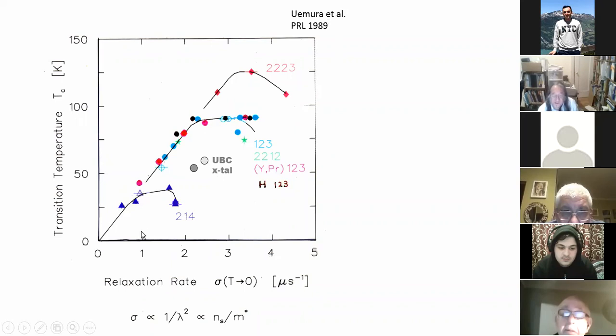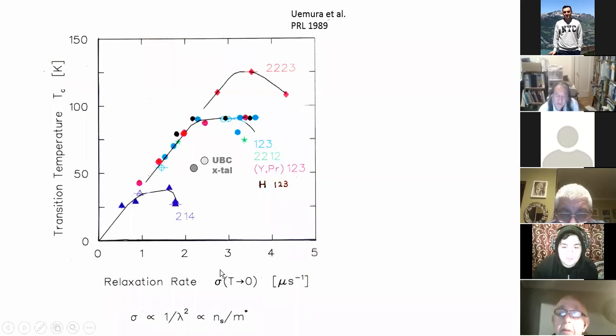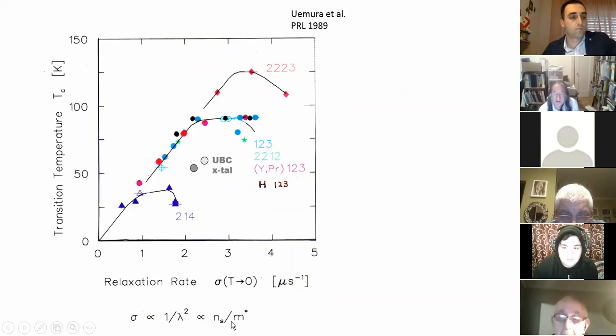And in the high TC cuprate systems, it is known that initially you dope superconductors with charges, essentially superconducting charges, and the TC increases and then shows some saturation and then decreases. But this initial increase area is called the underdoped region. And this data is showing that TC of this high TC cuprate superconductor, at least in this initial increase region with the doping, is related with a nearly linear relationship with this superconducting carrier density divided by the mass. So I'm sorry, these points were here. I moved this slide and I forgot to move these points together back again. But all these samples show a sort of common ratio between TC and the superfluid density. So this means that TC is very strongly related to the superfluid density.